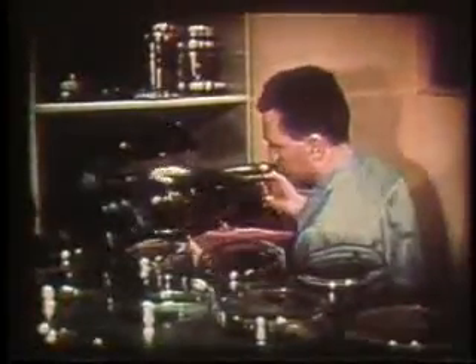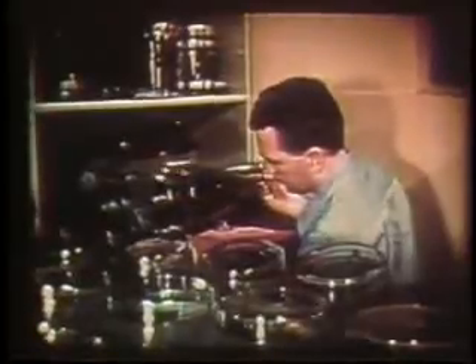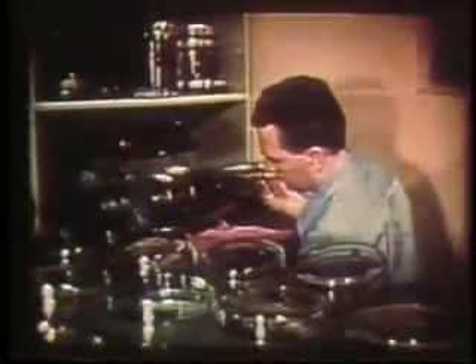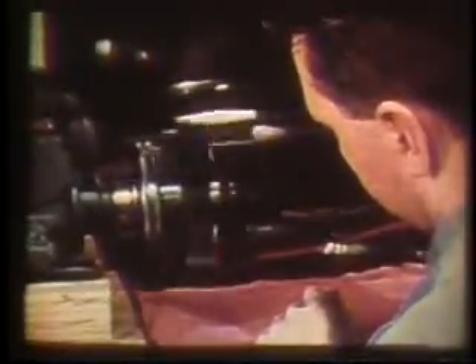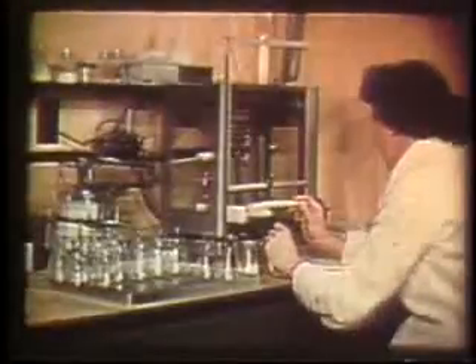This ink consists of finely milled carbon particles suspended in a special binder. Ethyl silicate is added to slightly dissolve or etch the glass as it is applied, thereby bonding itself firmly to the envelope wall. DAG is applied to the ends of the tube to make contact between the resistive spiral and the post-acceleration terminal. The envelope is baked at high temperature to dry and set the resistive material and the DAG.